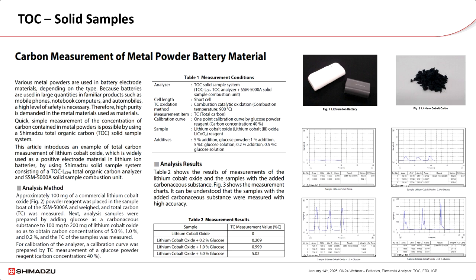In one study, Shimadzu used the TOCL and the SSM 5000A solid sample module to analyze commercial lithium cobalt oxide powder. First, a small amount of the lithium cobalt oxide powder was measured by the instrument. Then 3 separate aliquots of this powder were spiked with glucose to obtain an added carbon concentration of 0.2%, 1%, and 5%. These samples were then measured by the instrument in the same manner as a raw lithium cobalt oxide